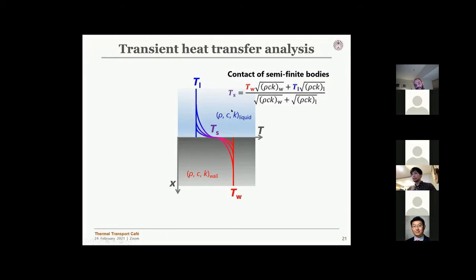From this model, we can get the surface contact temperature, somewhere around here, by using just these parameters that we know. We know the wall temperature, we know the droplet temperature, and we know the thermal properties of the sample and the droplet, right?